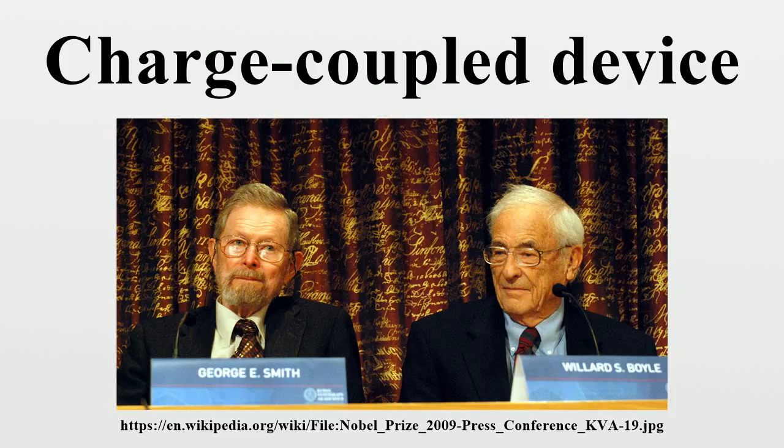Design and manufacturing. The photoactive region of a CCD is, generally, an epitaxial layer of silicon. It is lightly p-doped and is grown upon a substrate material, often P++. In buried channel devices, the type of design utilized in most modern CCDs, certain areas of the surface of the silicon are ion implanted with phosphorus, giving them an N-doped designation. This region defines the channel in which the photogenerated charge packets will travel.